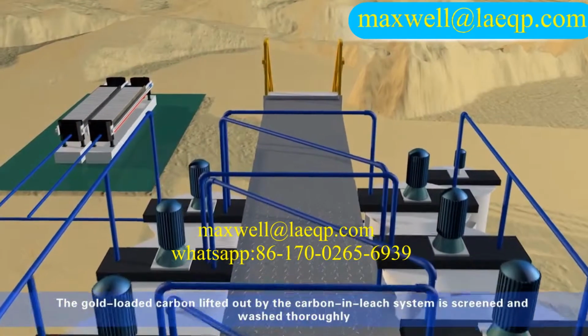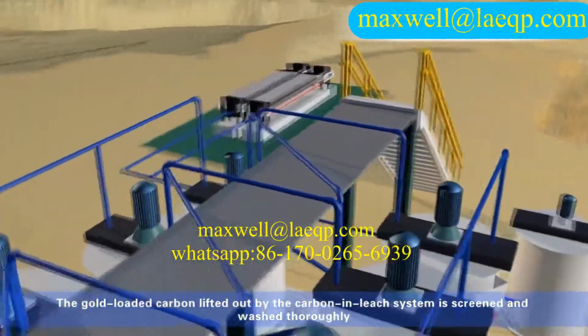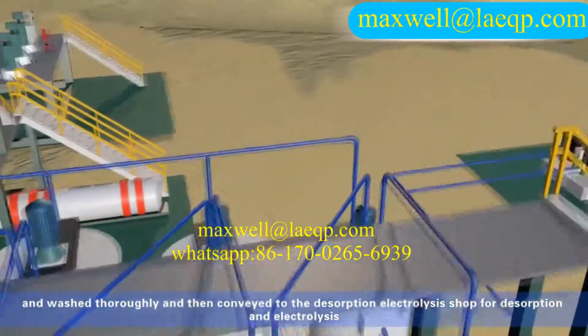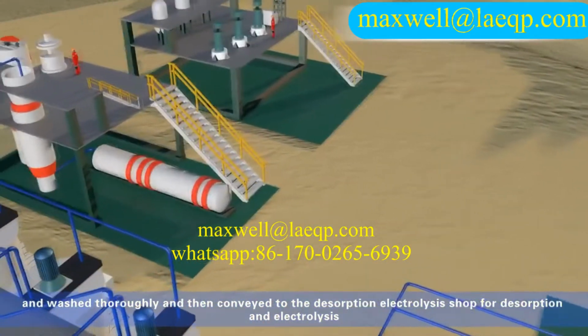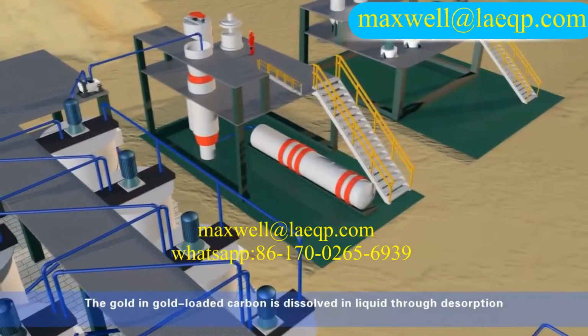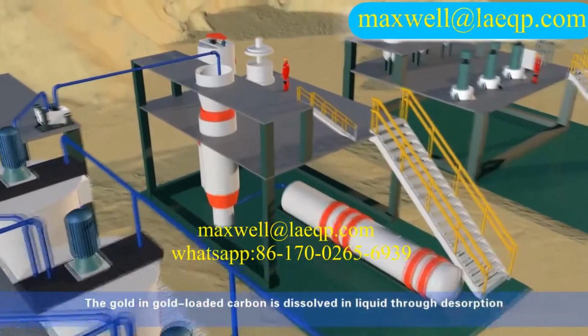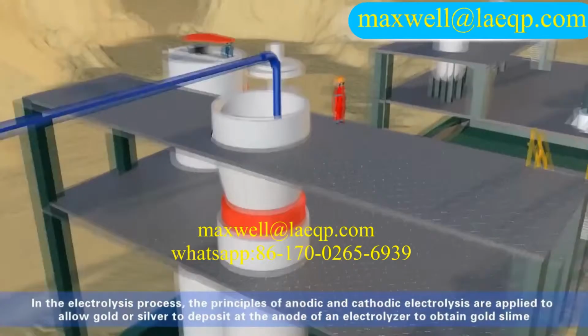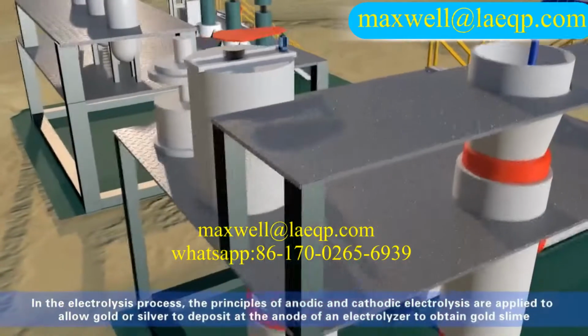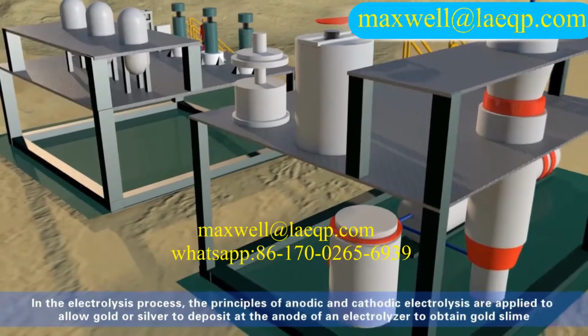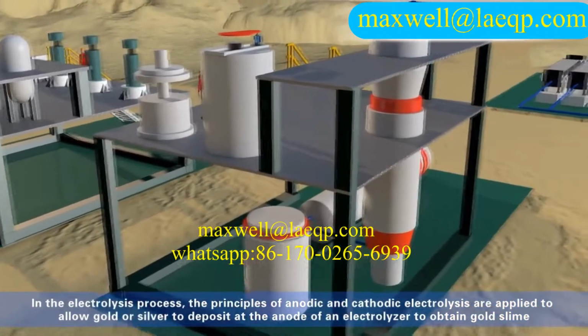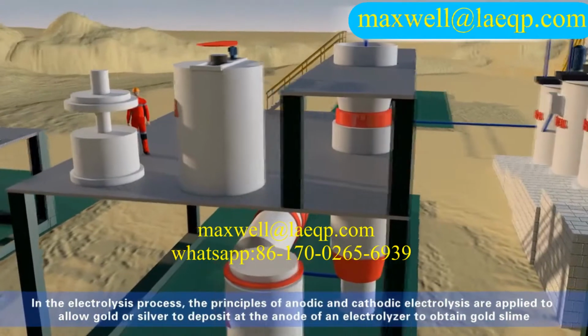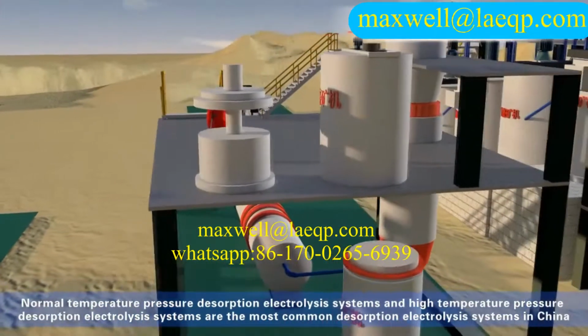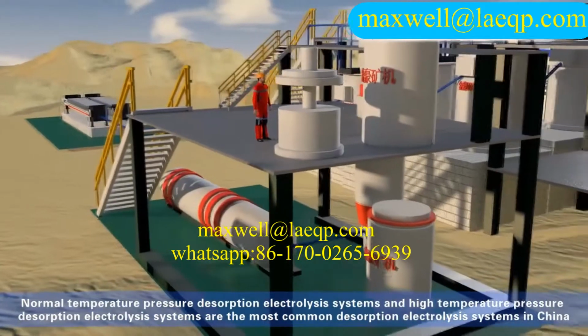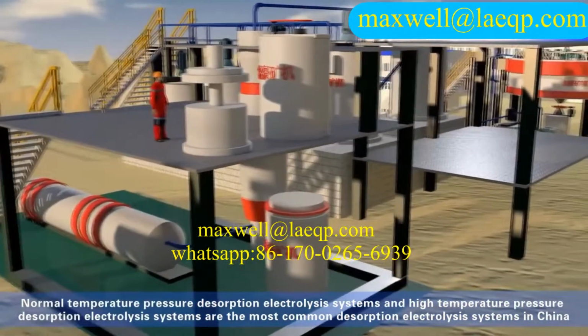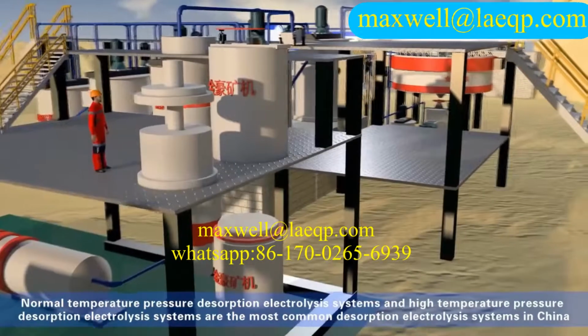The gold-loaded carbon lifted out by the carbon-in-leach system is screened and washed thoroughly, and then conveyed to the desorption electrolysis shop for desorption and electrolysis. The gold in gold-loaded carbon is dissolved in liquid through desorption. In the electrolysis process, the principles of anodic and cathodic electrolysis are applied to allow gold or silver to deposit at the anode of an electrolyzer to obtain gold slime. Normal temperature pressure desorption electrolysis systems and high temperature pressure desorption electrolysis systems are the most common desorption electrolysis systems